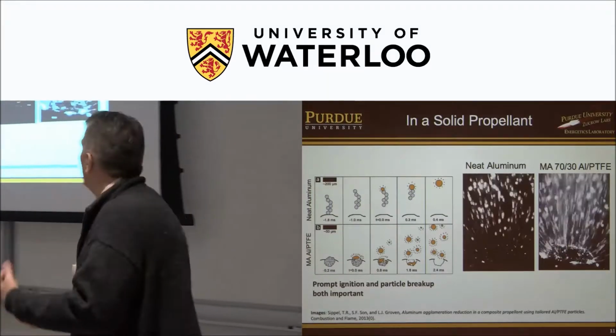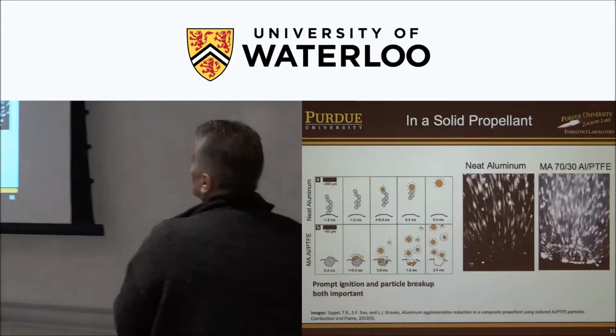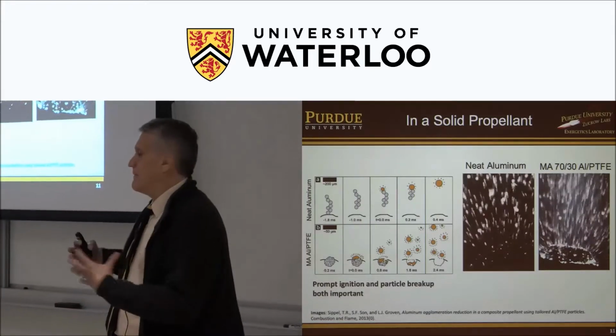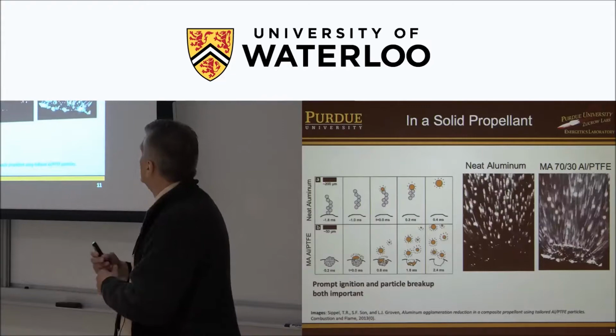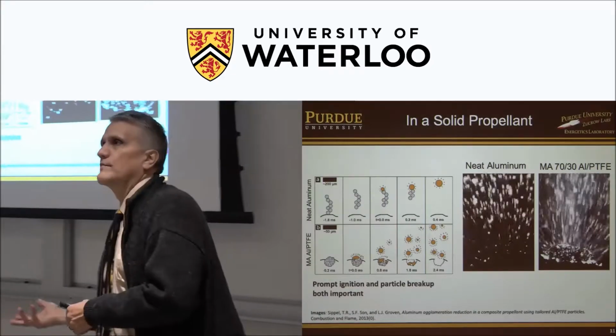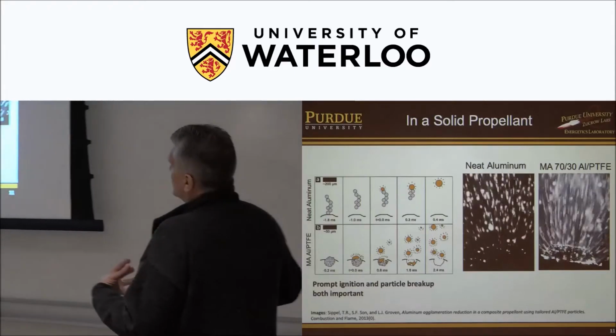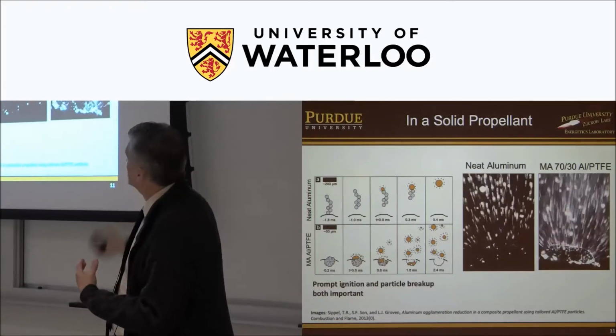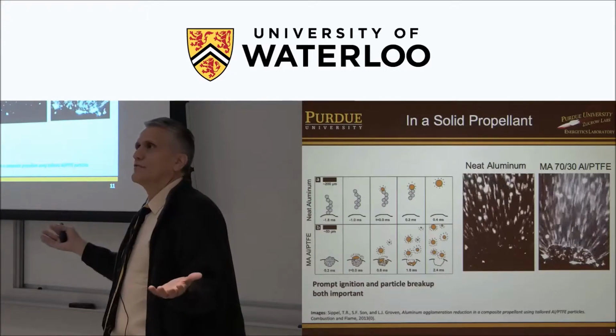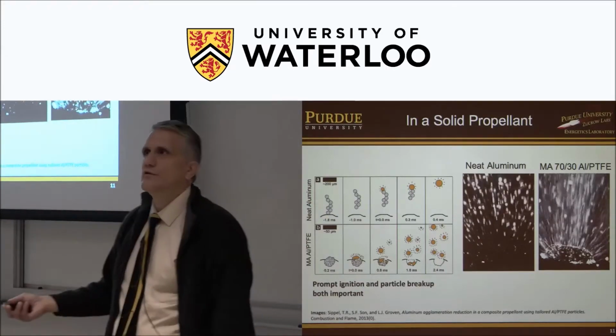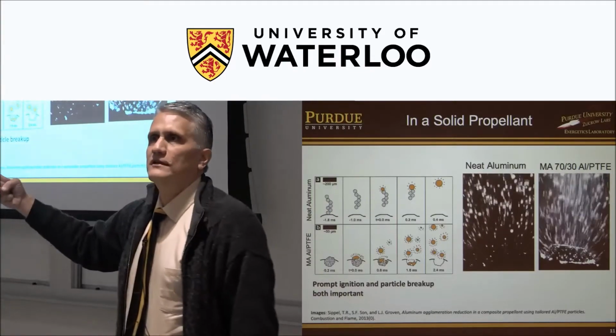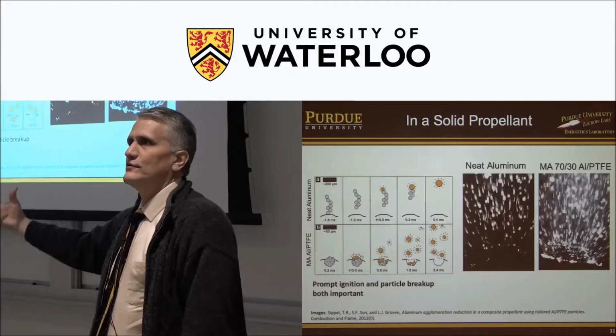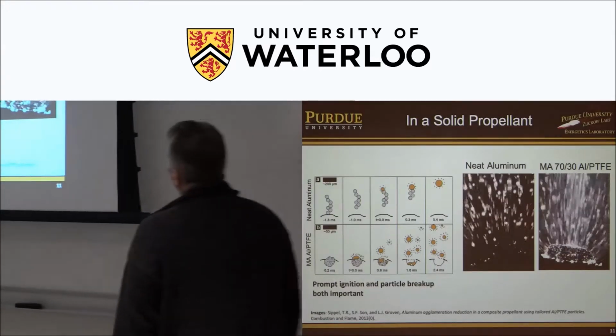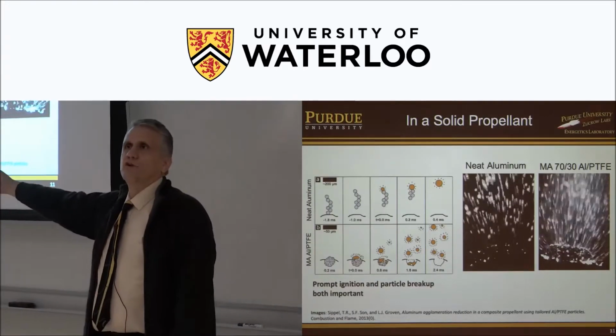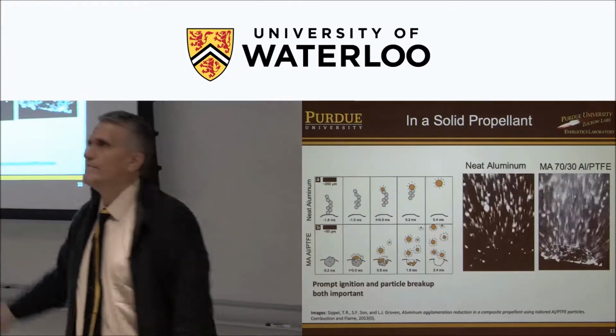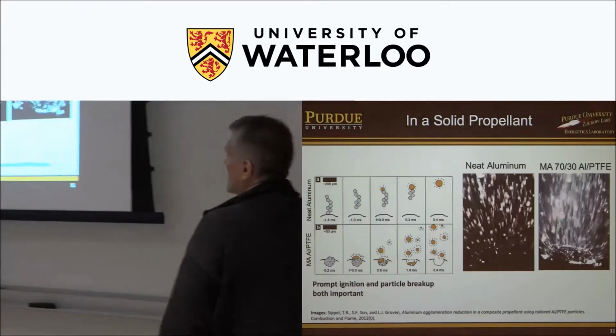Combustion efficiency, especially in small rocket motors. And also there's a loss that occurs, called a two-phase flow loss in rocket motors. So as the products of the combustion, what does aluminum go to? When it's oxidized, it goes to alumina, Al2O3. And in a rocket motor, that's liquid. So you actually have liquid droplets of combusted aluminum that clunk their way out through the nozzle. It can also be slag in the rocket motor. Neither of which help your performance. They cut into your performance.